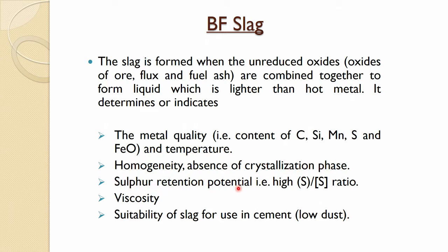Sulfur retention potential, so a high ratio of sulfide capacity, that is sulfur in slag to sulfur in metal. So, this also tells about the sulfur retention capacity of the blast furnace slag. Viscosity is another important aspect of the slag, whether it is highly viscous or has a low viscosity, because that will affect the refining or transfer of the element between the metal and slag